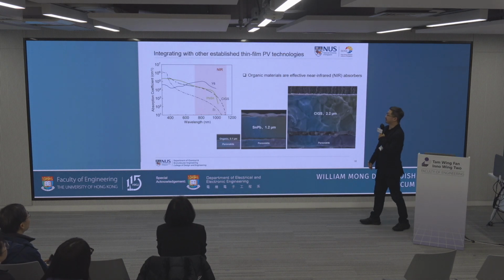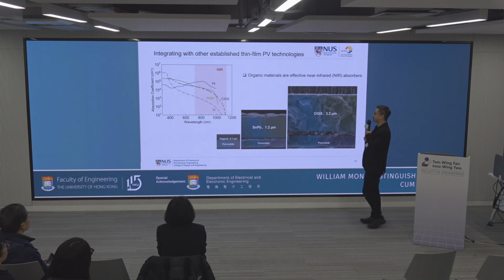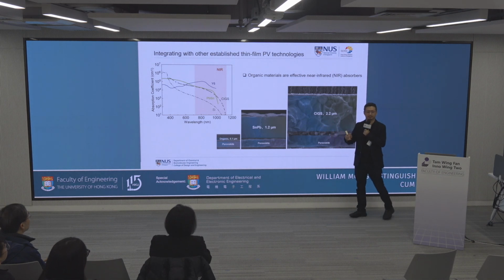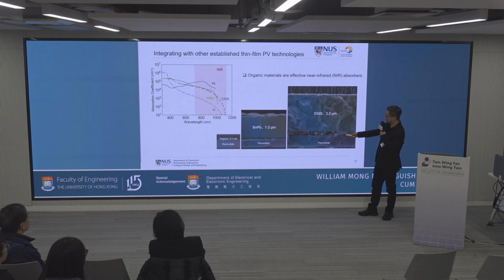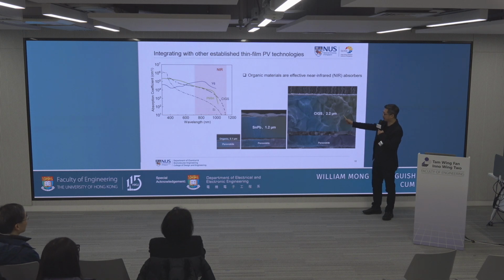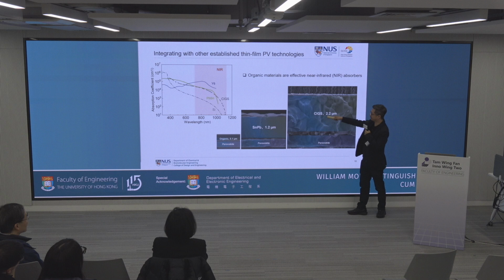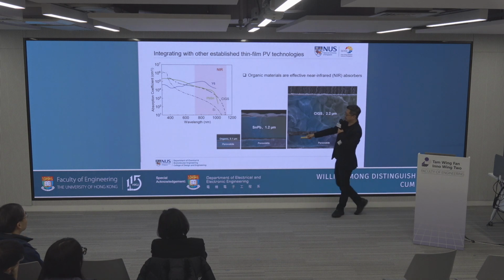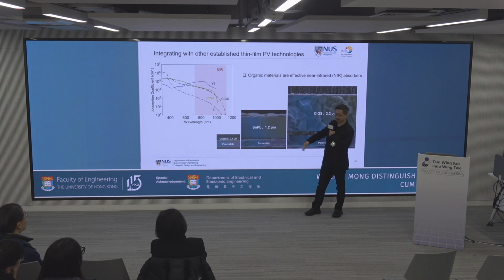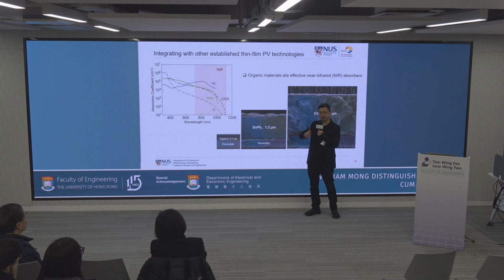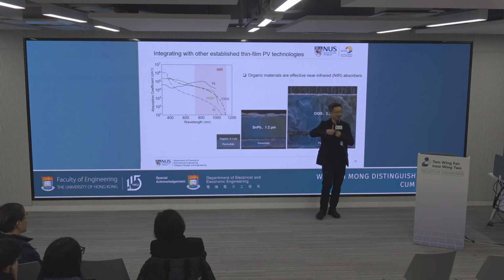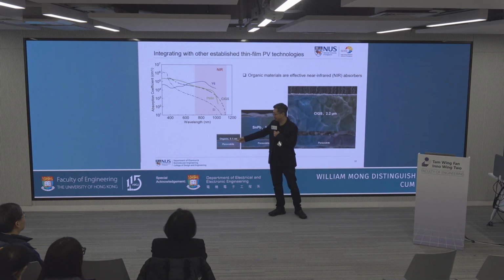So if you look at this perovskite-based thin film technology, you can see there's different partners can make this thin film tandem with perovskite. So this is the cross-section of the perovskite CIGS. We're working on this, but if you look at the CIGS, it's very thick. It's about 2.2 micron. And this is a perovskite tandem, and Mercouri just mentioned. And this one, because we want to better enhance this near IR photons. So the trend right now is to make this thin light perovskite thicker and thicker to capture more photons. But this brings another challenge. You need to overcome the recombination, because diffusion length is longer. So you need to avoid recombination. But another one is perovskite OPV.